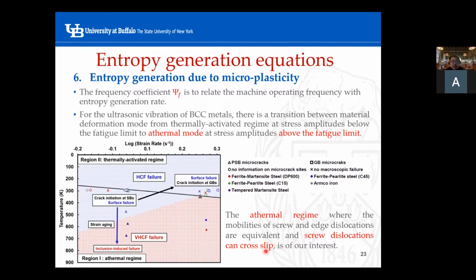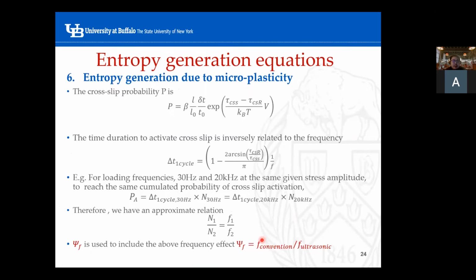So the micromechanism here is the cross slip of screw dislocations for the ultrasonic vibration fatigue that belongs to this region. This cross slip of the screw dislocation is actually frequency dependent. As you can see, this is an equation obtained during the literature review.